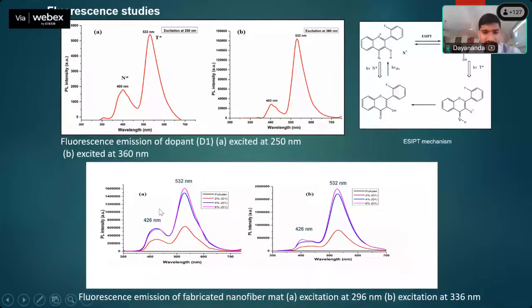See the peaks: for the dopant, the first peak was at the nanofiber mat, it was 426 nanometer, so it was not the same as the dopant. The bathochromic shift of 26 nanometer could be mainly due to the J aggregation.